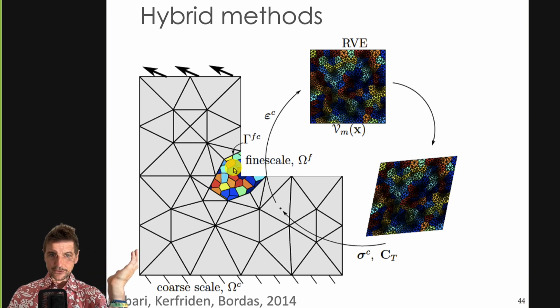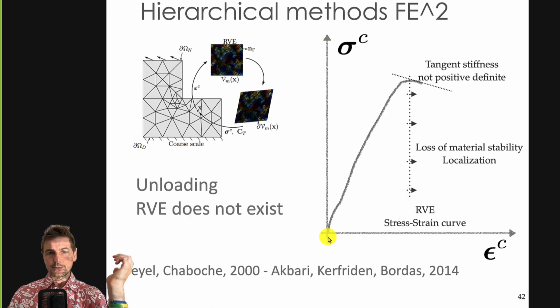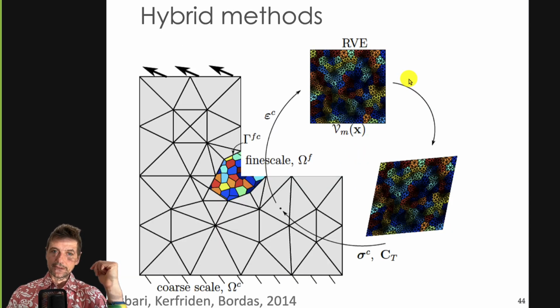Otherwise, they will have no memory, they will be unloaded, so you would introduce them here, which is completely wrong because you reach the peak. So you want to reload all the microstructure until you get to here, which is very difficult because you need to unload everything and reload everything now with the real microstructure in there, which is extremely computationally intensive and would need to be accelerated, maybe using methods such as machine learning.